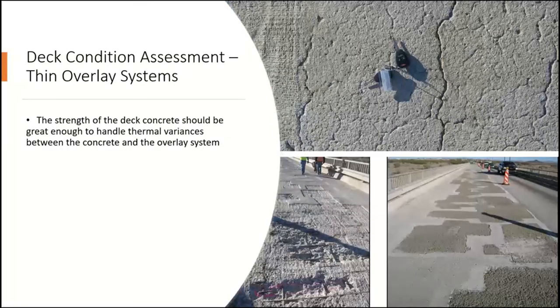Like I said, one of the most important things is the condition of the deck. I like these photos because, and I'm not going to mention the state, they chose about 5 bridges for the first trial, and they all look very similar to this one on the bottom left, as you can see. When you consider a thin polymer overlay, the biggest thing to keep in mind is that it does expand and contract at a higher rate than the concrete deck itself. Maybe as many as 4 or 5 times faster.